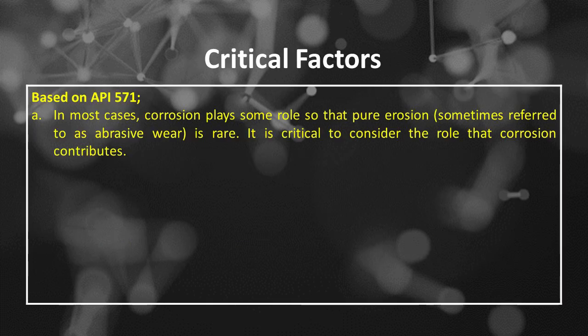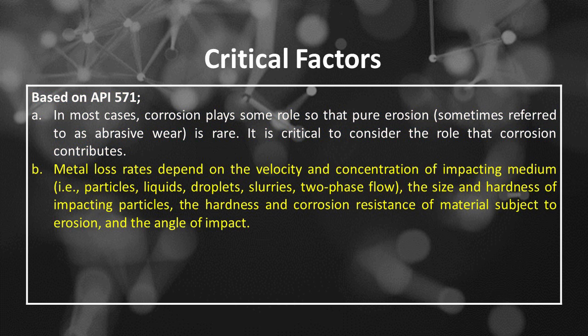Erosion and erosion-corrosion based on API 571. The first is in most cases, corrosion plays some role so that pure erosion, sometimes referred to as abrasive wear, is rare. It is critical to consider the role that corrosion contributes. The second is metal loss rates depend on the velocity and concentration of impacting medium, such as particles, liquids, droplets, slurries, two-phase flow, the size and hardness of impacting particles, the hardness and corrosion resistance of material subject to erosion, and the angle of impact.